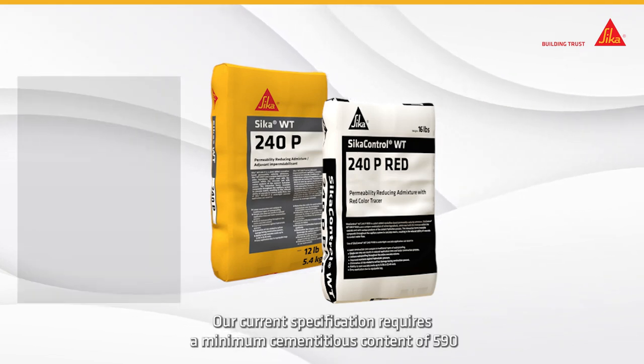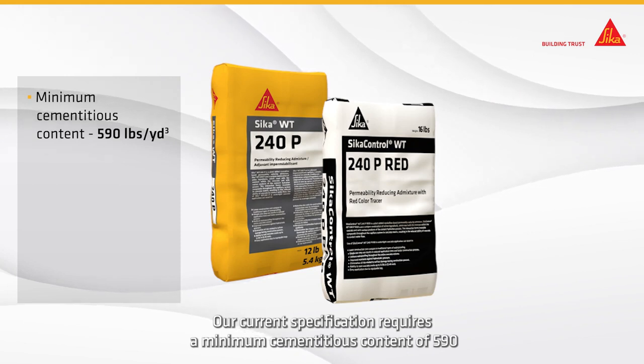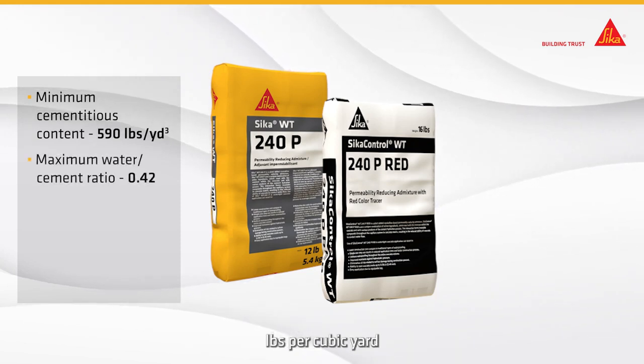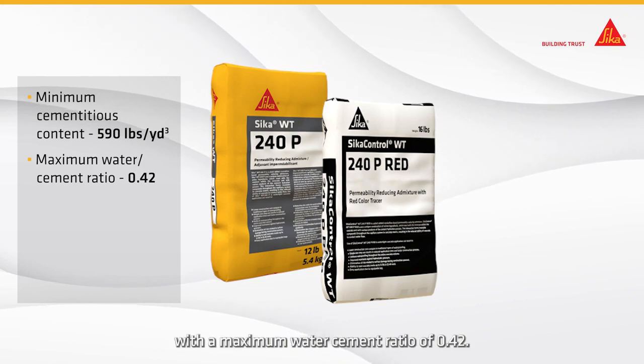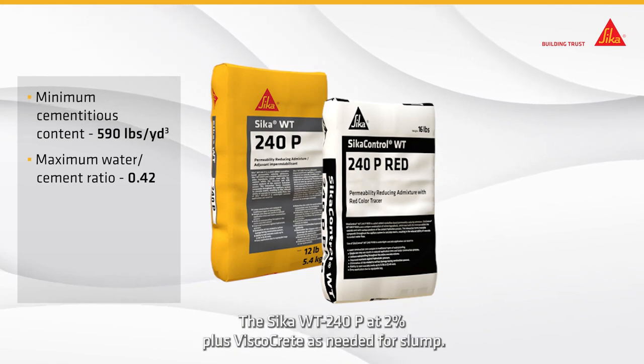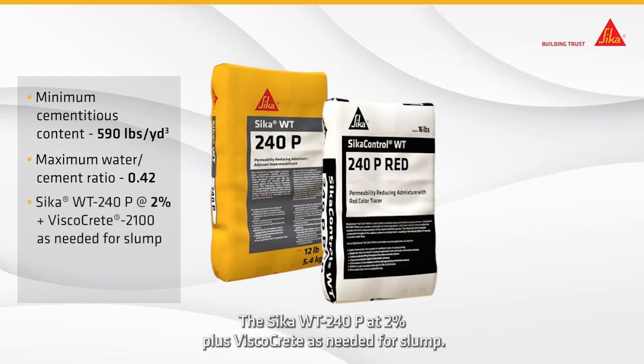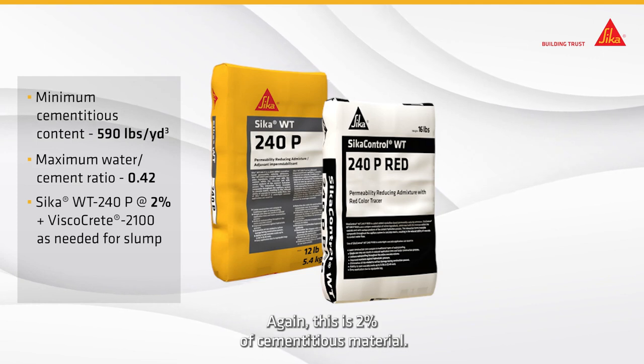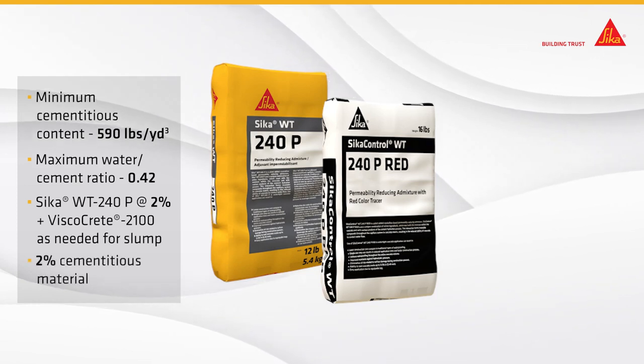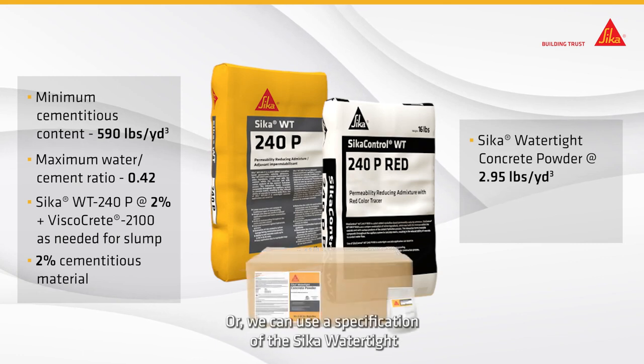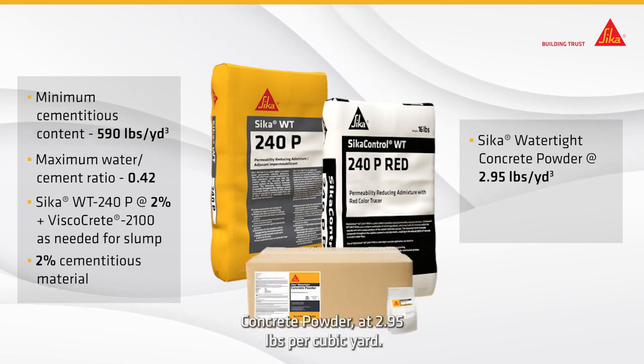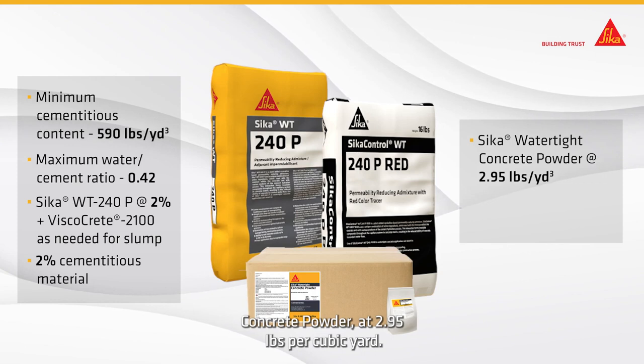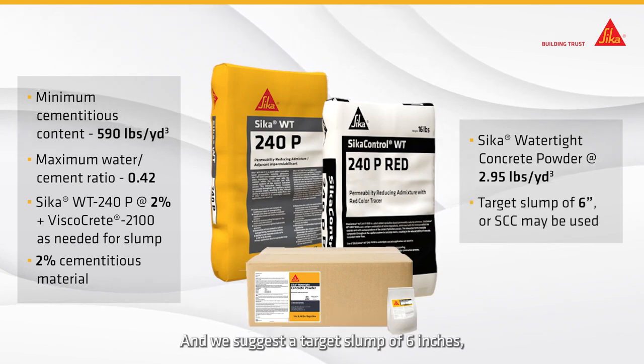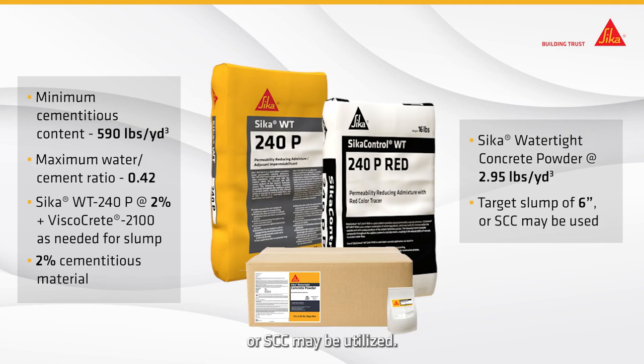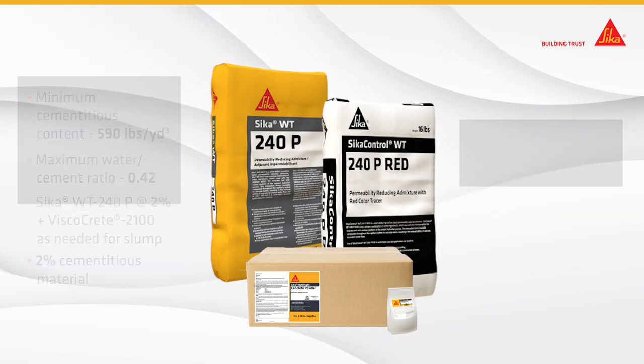Our current specification requires a minimum cementitious content of 590 pounds per cubic yard, with a maximum water-cement ratio of 0.42, the Sika WT-240P at 2% plus Viscocrete as needed for slump. Again, this is 2% of cementitious material. Or we can use the specification of the Sika watertight concrete powder at 2.95 pounds per cubic yard, and we suggest a target slump of 6 inches, or SCC may be utilized.